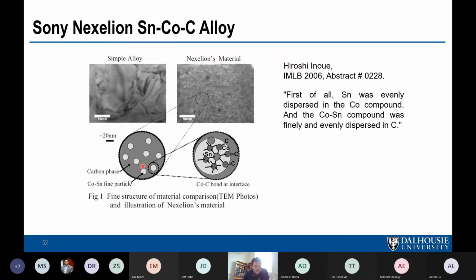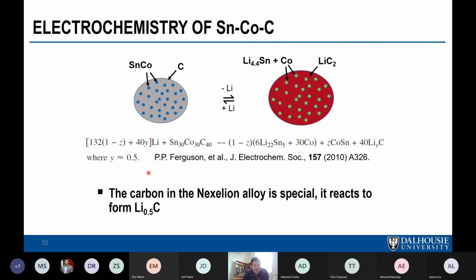And here, the matrix phase is carbon, so that can have capacity too. And the cobalt tin phase also is active, so this is a completely active particle. And yeah, this is the reaction, and a lot of it was figured out actually in Jeff's lab, how this is working. If you want to model the capacity of this, you have to assume that you're forming lithium a half carbon, which is a lot more lithium than you can put into graphite. And this is very special carbon. It's kind of mysterious too, because if you don't have this tin cobalt phase around and you just try to ball mill carbon, you're not going to get this nice capacity with low polarization. So it's still kind of mysterious to me how you can make this beautiful LiC2 carbon only when this tin cobalt phase is present.